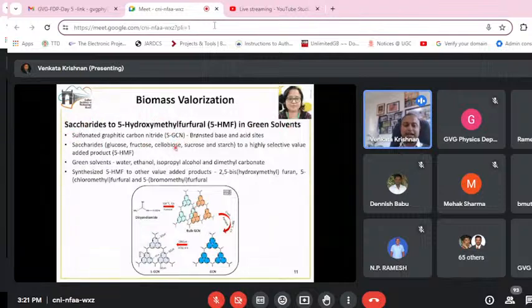We designed this catalyst, called the sulfonated graphitic carbon nitride catalyst, so that the single catalyst possesses both Bronsted base sites and Bronsted acid sites. The Bronsted base sites originate from the nitrogen moieties present in the graphitic carbon nitride, and the Bronsted acid sites come from the sulfonic acid (SO3H) groups functionalized onto this graphitic carbon nitride.